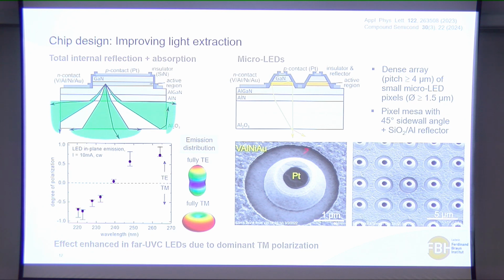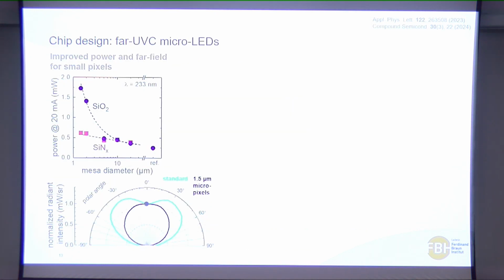And now what happens is light that is actually emitted laterally gets reflected because of this aluminium reflector, and then will come out of our device. And so we can actually improve the efficiency of our LED because we can collect more light out of the LED. And what you can see over here, the amount of light that we can collect from the LED is dependent on the size of these micropixels that we have, so these micro LEDs. And if you go to smaller diameters, then you can extract more light out of the LEDs because that's less distance that the light can actually travel in the system.